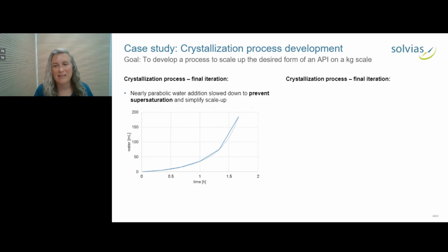One good way to do an anti-solvent dosage, rather than to just dose at a consistent rate, is to use a parabolic profile. The idea being that you add anti-solvent very, very slowly when your system is highly saturated, and then as more and more precipitates out, you can add it at a faster rate. We approximated this parabola with 4 linear ramps.